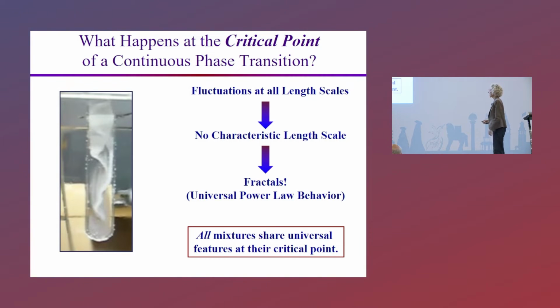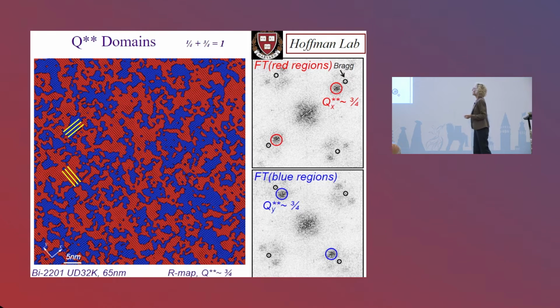So what's lovely here is that everything goes power law. And if we could zoom in and zoom in on the density in the critical areas, we would see that because it's power law, it's self-similar. It looks the same on different length scales as you zoom in, which means there's a fractal nature to it. It's a disordered fractal, but it's fractal in nature. And when you have this second order behavior, there's universality. So there's universal power law behavior in the sense that all mixtures share universal features at their critical point, such as the critical exponents. So what does that have to do with this pattern formation?